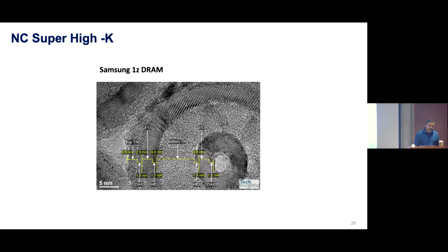We have also seen this use in Samsung's 1Z DRAM. Again, it went into production in 2020. DRAM is very well known to use a material called ZAZ, which is zirconium oxide, aluminum oxide, zirconium oxide. But from 2020, what we have seen is that a hafnium dioxide layer was introduced. Again, this is to help with the increase in capacitance, which then allows them to reduce the area of the DRAM cells.